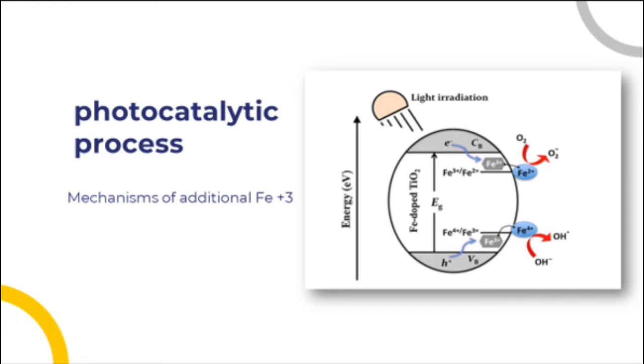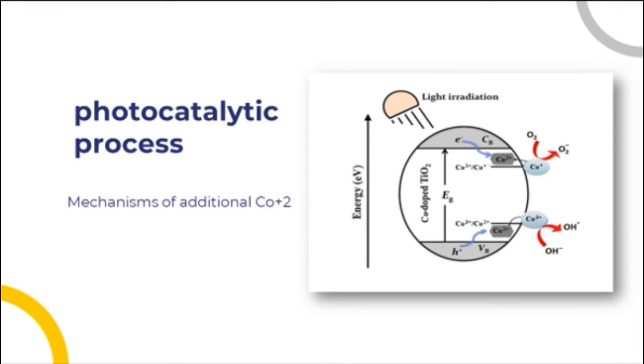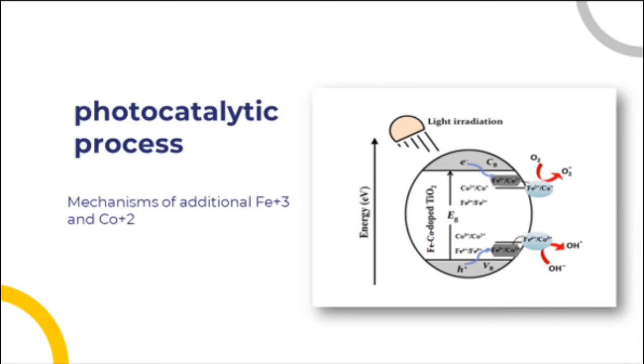In the meantime, Fe³⁺ ions can also act as hole traps because the energy level of Fe⁴⁺/Fe³⁺ is above the valence band energy of the doped titanium dioxide. Therefore, Fe⁴⁺ ions can be reduced to Fe³⁺ ions by capturing electrons while the surface hydroxyl group is transformed into a hydroxyl radical. We believe that the electron and hole scavenger ability of Fe³⁺ ions is the main feature that helps to explain the higher photocatalytic activity observed for our Fe-doped titanium dioxide sample. The same mechanisms happen for cobalt-doped titanium dioxide and the mix of iron and cobalt doped titanium dioxide.